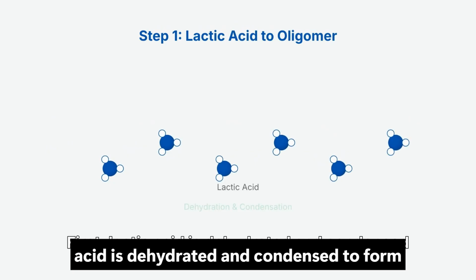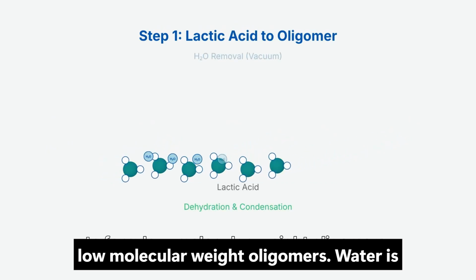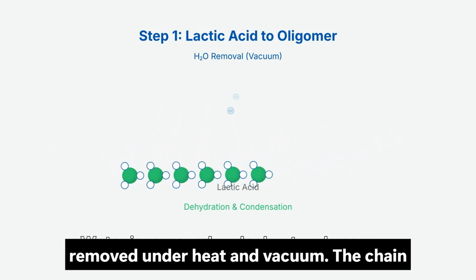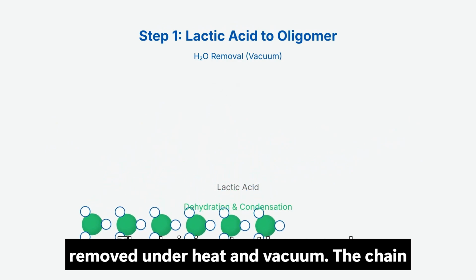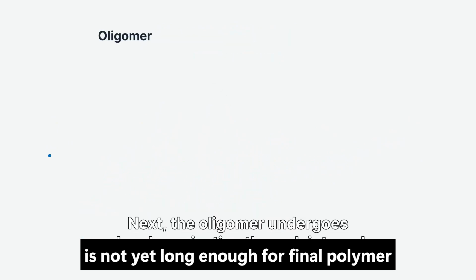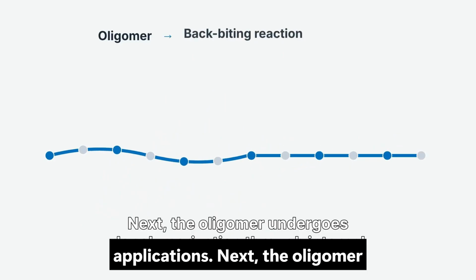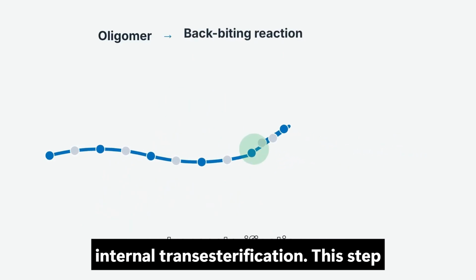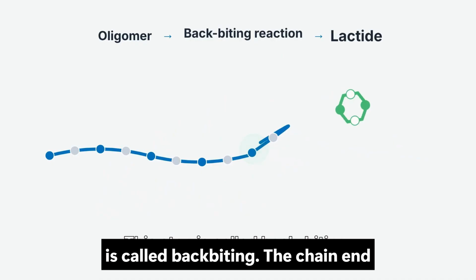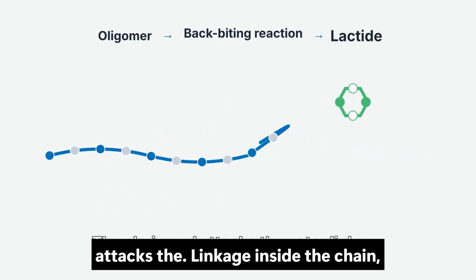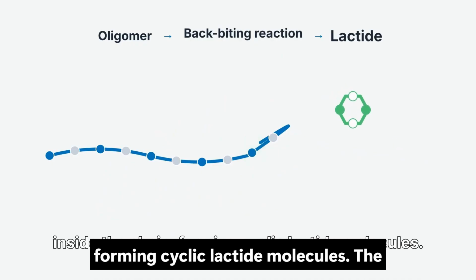First, lactic acid is dehydrated and condensed to form low molecular weight oligomers. Water is removed under heat and vacuum. The chain is not yet long enough for final polymer applications. Next, the oligomer undergoes depolymerization through internal transesterification. This step is called backbiting. The chain end attacks the ester linkage inside the chain, forming cyclic lactide molecules.